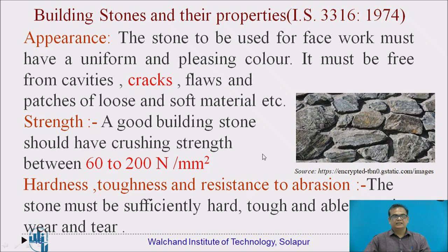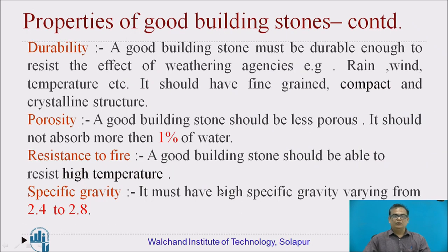Building stones as per IS 3316: their appearance should be good. When used for face work, they should have a uniform, pleasing color and must be free from cracks, cavities, and flaws. Crushing strength should be from 60 to 200 N per mm². Hardness, toughness, and resistance to abrasion should be good. Durability should be good. Porosity should be less porous — not more than 1% water should be absorbed. Resistance to fire should be present. Specific gravity should be from 2.4 to 2.8.